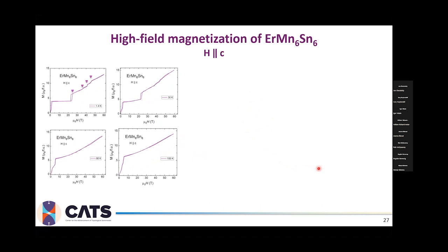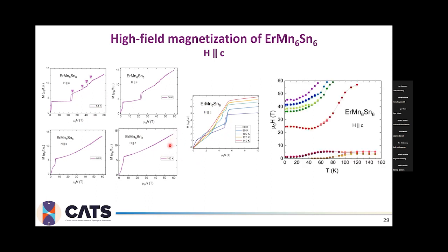When we apply the magnetic field along the C direction, as I showed earlier, we have one transition around 25 Tesla, with hysteresis, followed by three different peaks. Again, in that case, when we are above 91 Kelvin, we can see that in the low field there are multiple steps and new transitions showing up. However, in the high field it is just that transition which is slowly getting pushed into the higher field. The interesting part is that we do not really see the bubble fully. What we think we see is just the bottom part of it.